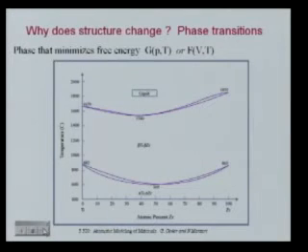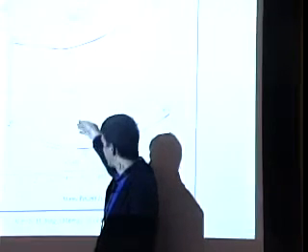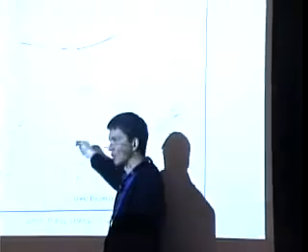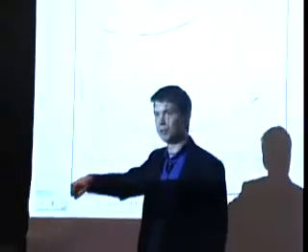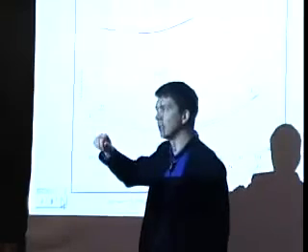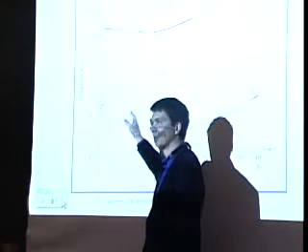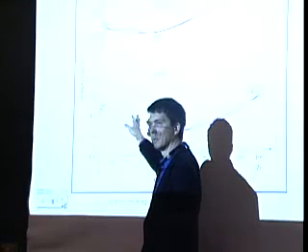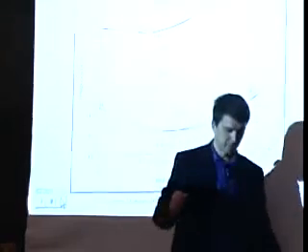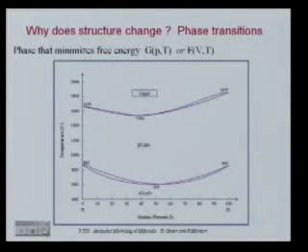or anything close-packed at low temperature to something less close-packed? Most people will argue that it is the atomic vibrations, that is essentially a vibrational entropy difference. Okay? The close-packed phase tends to be stiffer. The less close-packed phase tends to be softer. Remember, softer means lower frequencies. Lower frequencies means higher entropy. Higher entropy means you become favored at high temperature. I know there's a lot of steps to go through, but if you've never done thermo, you should get this by now. Okay? So if that's true, then our perfect ab initio MD would get this transition.